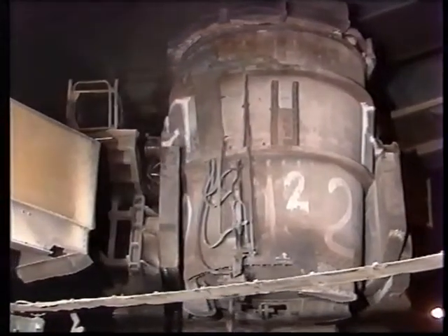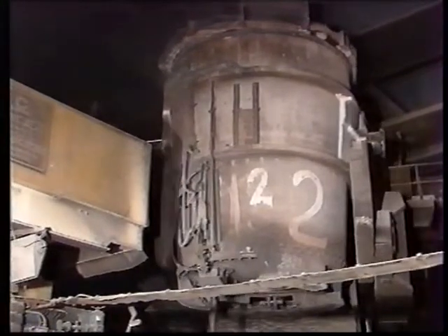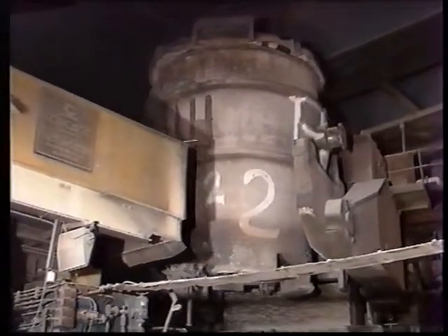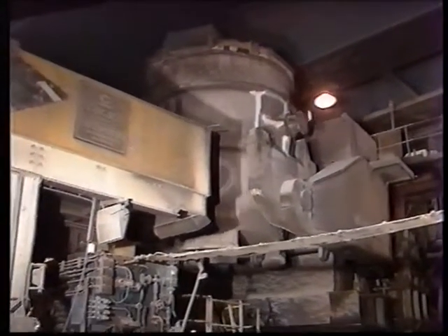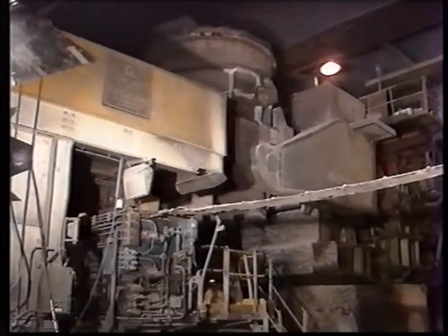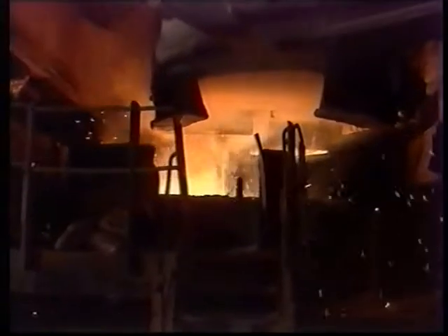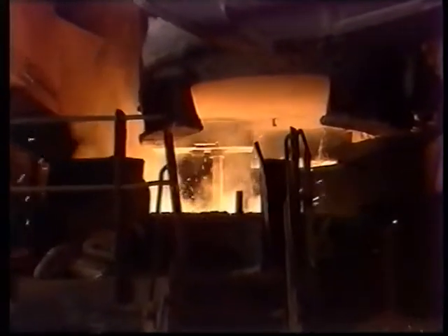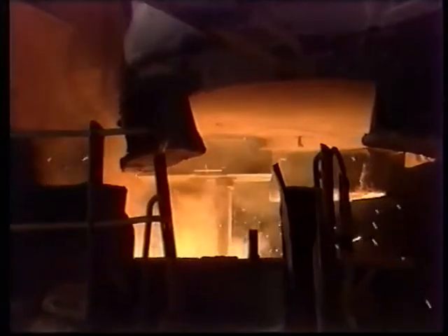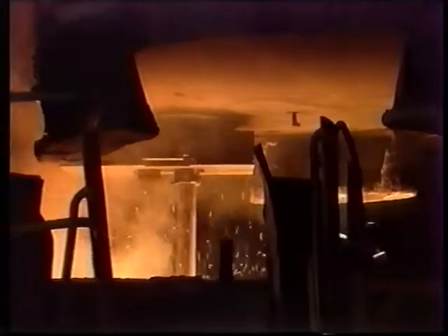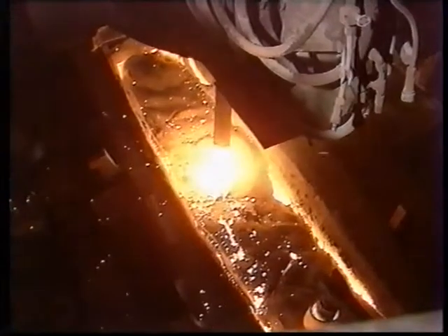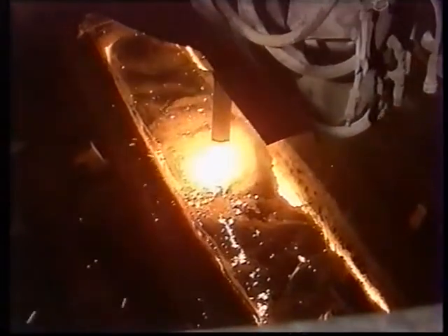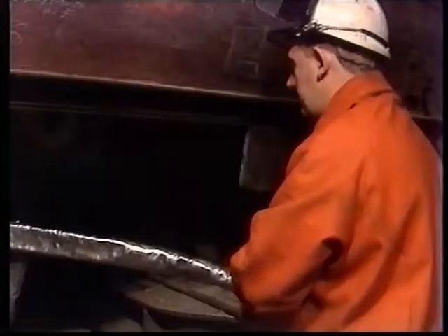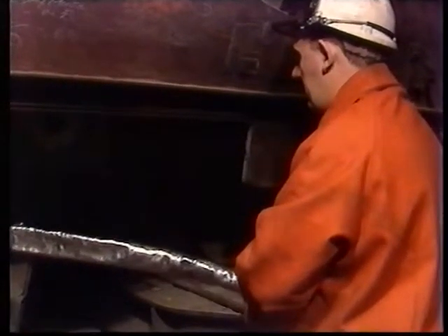When the temperature of the steel is correct, the ladle of steel is taken to the continuous caster. The rotating turret takes the ladle from the steel-making bay to a position over the casting machine, from where the molten steel is teemed into the tundish through an enclosed refractory tube which mates precisely with the gate valve in the ladle bottom. It is the tundish which provides a constant flow of steel to the concast mold, using an electronically controlled flow management system.